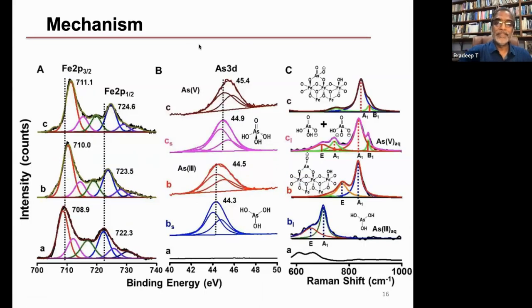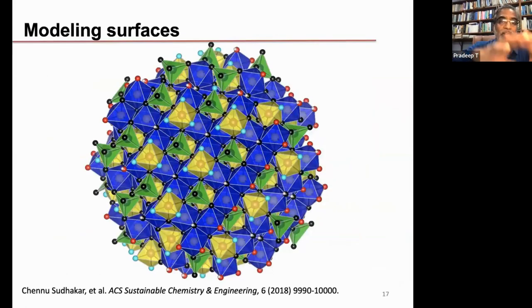But what is important is that if you have an iron oxyhydroxide of this kind of structure, you can put arsenate ion as well as arsenite ions on the surface. And you can observe this by spectroscopy. What is shown here is Raman spectroscopy. So what you see is both arsenate and arsenite ions sit on the surface. Effectively, both are removed. So on a nanoparticle of this kind, you do understand where exactly or what kind of adsorption sites are there to remove both of these. So you can do a synthesis, optimization of the synthesis to create the best adsorption sites on the surface, and a most effective material can be made.